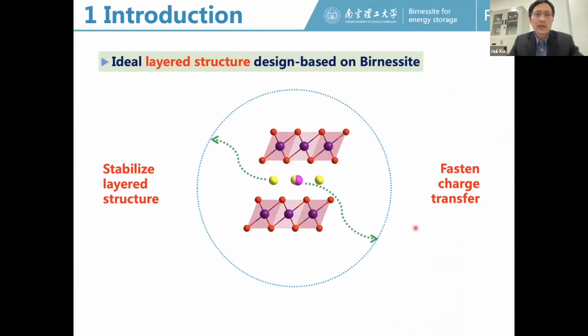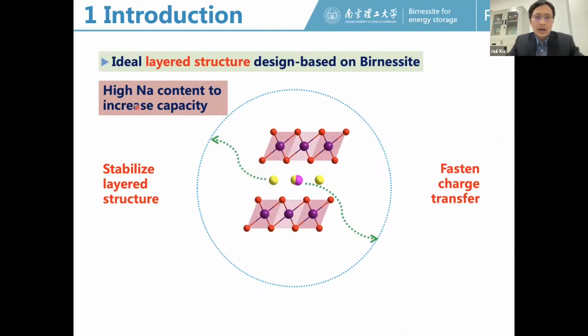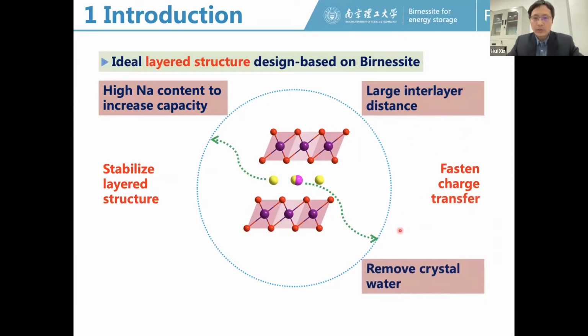For this work, we are trying to design an ideal layered structure based on the Birnessite structure for sodium storage. So first, we will need a high sodium content to increase the capacity, and then we will need a large interlayer distance to enable fast sodium ion diffusion. And we also need to reduce the crystal water content, because there is a trade-off between the high sodium content and the crystal water content. If we have too much crystal water, we cannot increase the sodium content.